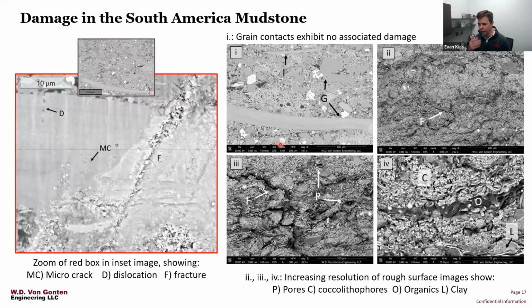The remarkable thing about the Vaca Muerta sample is that it really wasn't apparent what the damage mechanism was. It was actually quite difficult to find the damage. That's why on the left side of the screen here, I'm highlighting a very small window of that previous image to show some of the damage that was obvious in the sample. Throughout this grain, we have a fracture that propagated through it, a dislocation event, and also some micro cracking that occurred. Notably though, the rest of the sample seemed largely intact.